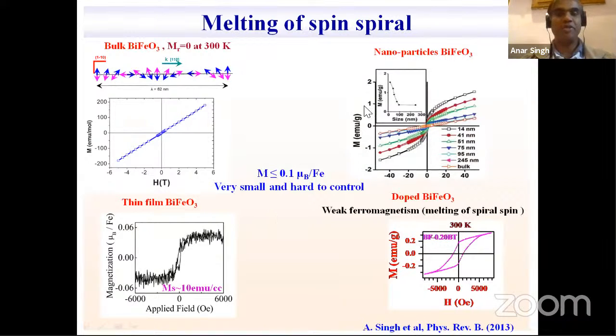So these are the possible ways by which we can suppress the spiral spin structure. See here, this is the MH curve for bulk bismuth ferrite, and we can see that there is no macroscopic magnetization, no ferromagnetic component. But in the case of epitaxially strained thin films, we have some ferromagnetic component, which is less than 0.1 mu B per Fe. And in the case of nanoparticles of bismuth ferrite, if we reduce the size of the particle below the periodicity of the spiral spin structure, which is 62 nanometers, then for nanoparticles having size less than 62 nanometers, we have some ferromagnetic component. So this is another way of melting the spiral spin structure.